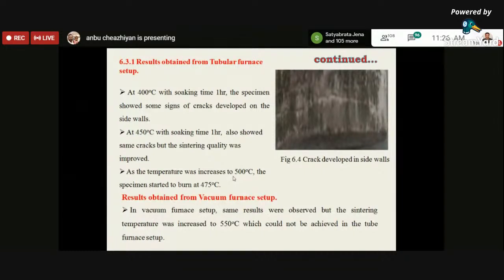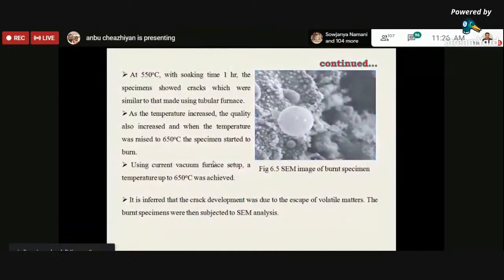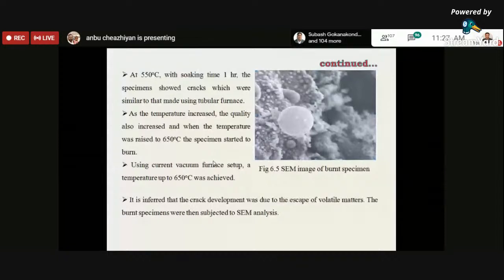In the vacuum furnace setup, we increased to 550 degrees centigrade. The soaking time was maintained at 1 hour. It showed the same cracks, similar to those in the tubular furnace. As the temperature was increased to 650 degrees, the specimen started to burn. So this is what we obtained.